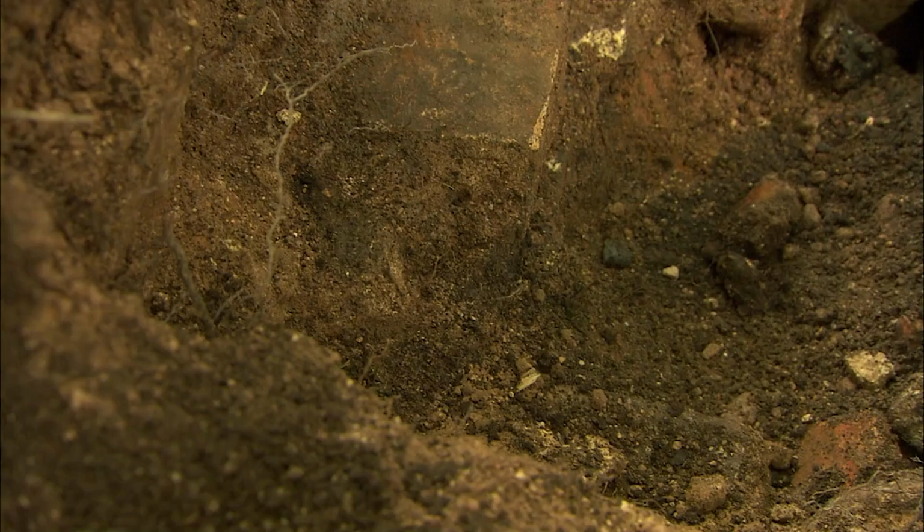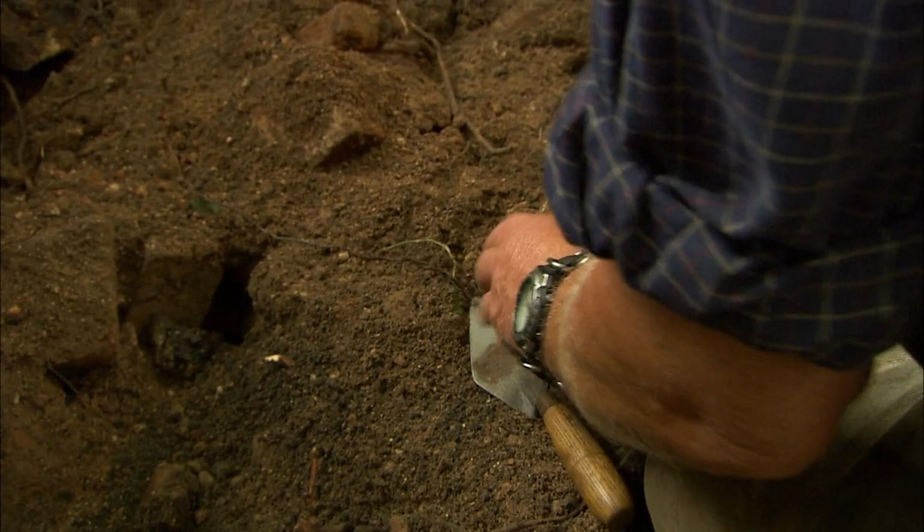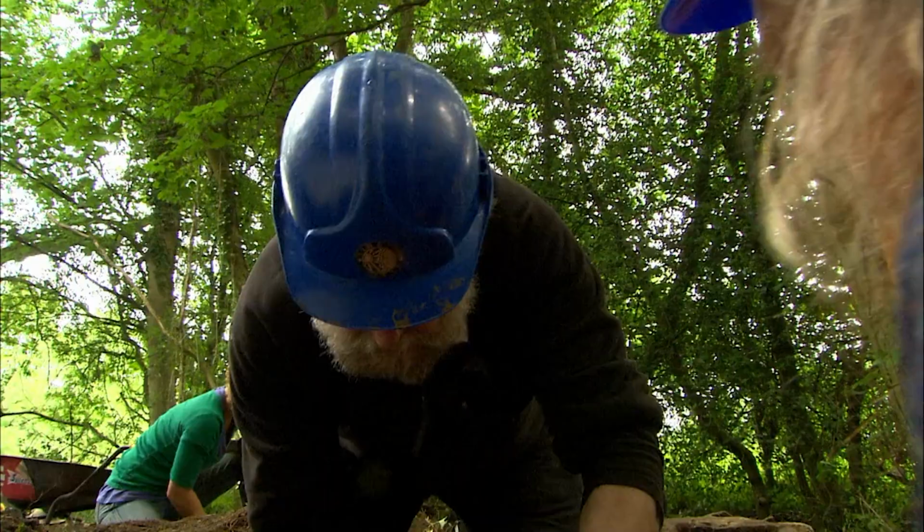And look, you've got a very clear edge of all this material coming round here between the burnt material there and this black stuff on there. But the really crucial thing that does really bring it home is not just the colour of these bricks, but look, they're fused together. I mean, that's fantastic. To me, that is the hot face of a crucible furnace.